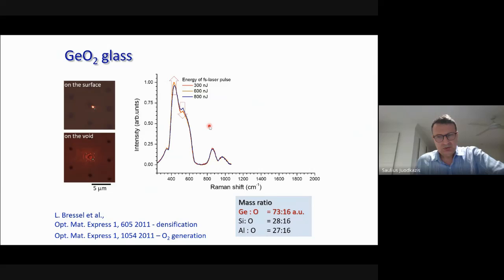To do this type of experiments in synchrotrons is not so easy and simple. So we looked at how we can prove that ionization and decomposition of material with something more simple. So we took germanium oxide glass. And why germanium oxide? Because the ratio of masses is much larger. So separation during this explosion, that movement, should be more efficient to separate germanium from oxygen. If you compare aluminum oxides, aluminum and oxygen, their masses are closer.